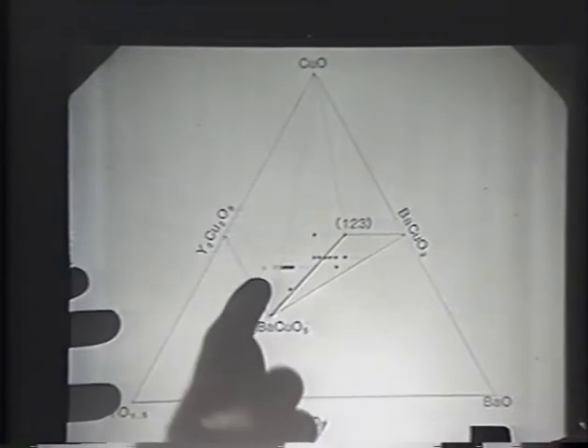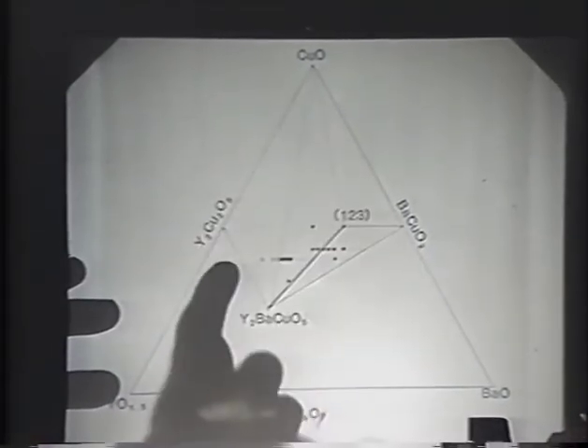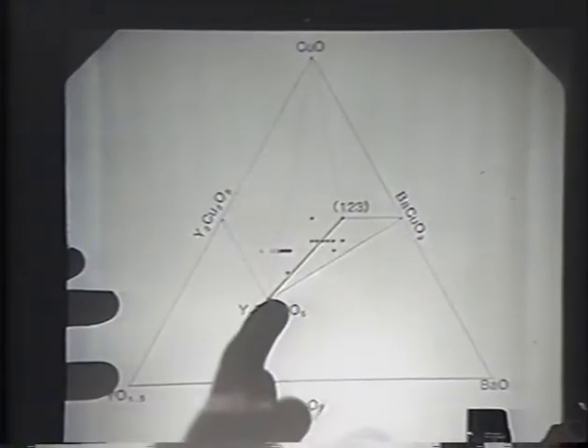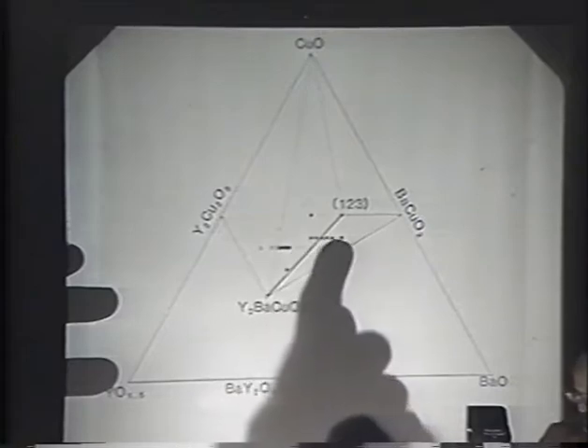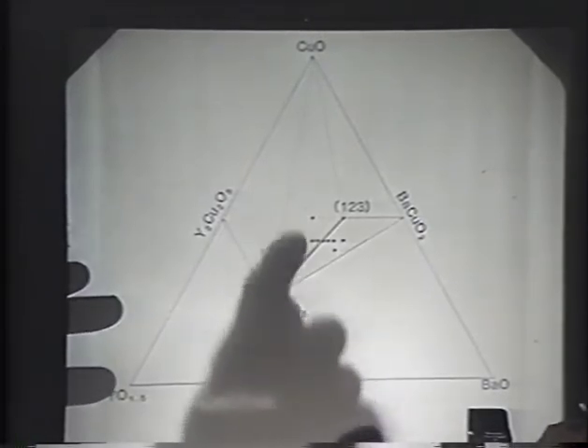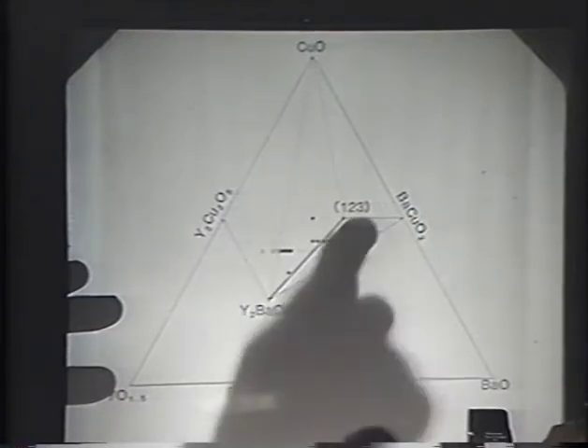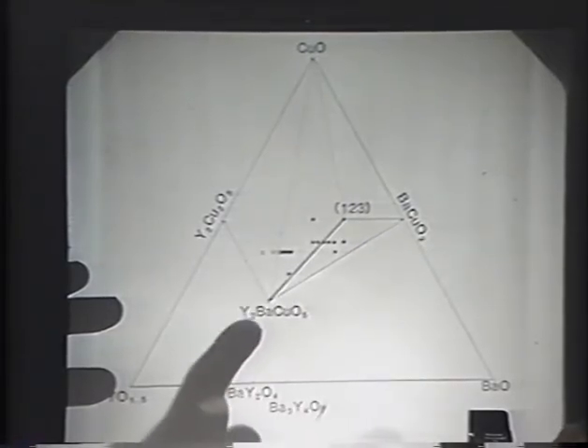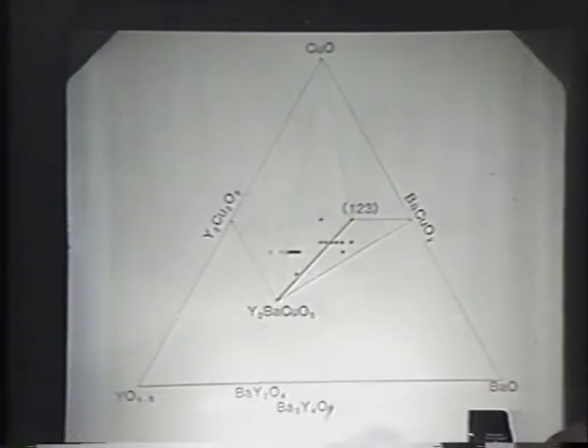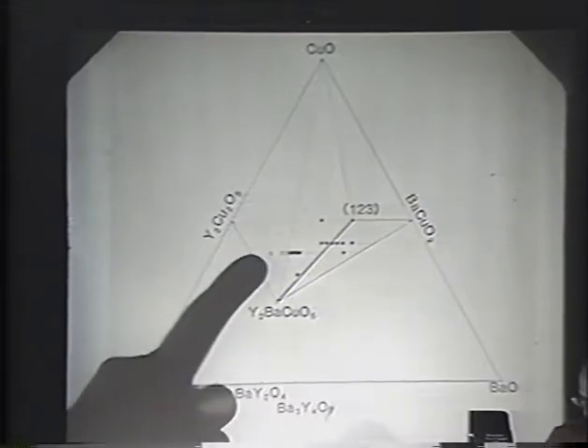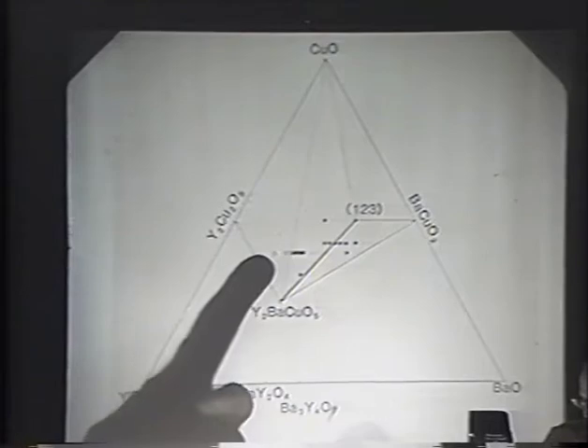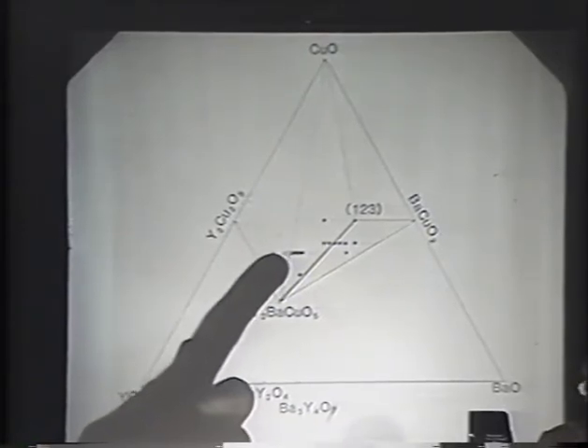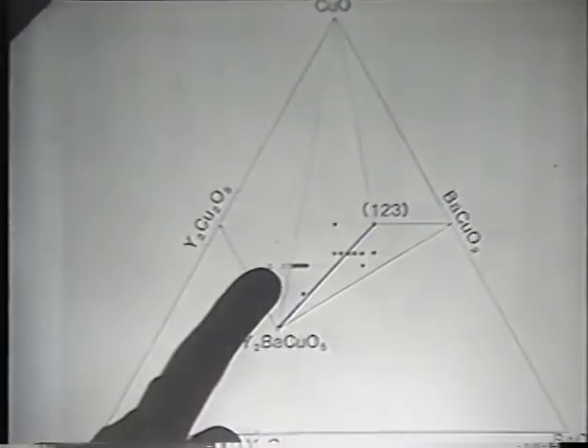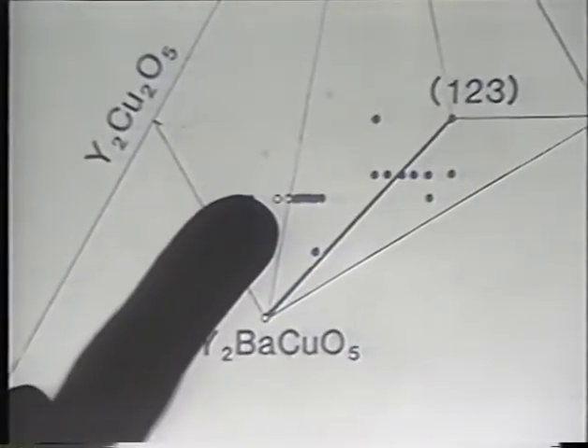And we have done 2 careful slices at constant copper composition, one cutting across a possible line here and one cutting across a line here. And we see interesting things going on as you cross this line, the join between the green stuff and the black stuff. You see that we've drawn these circles open here to the left of this line. So there's 3 points that show no diamagnetic signature whatsoever, no superconductivity as determined from diamagnetism, and then a string of black dots.